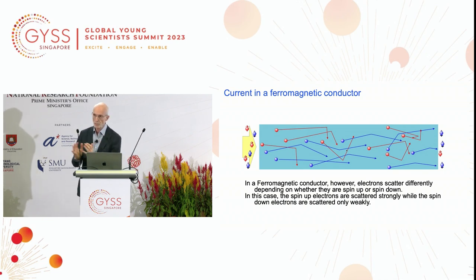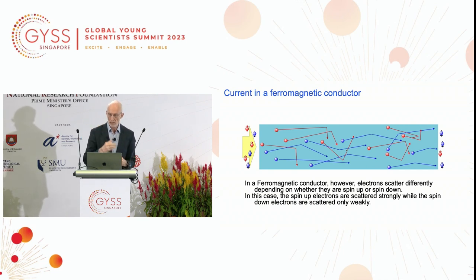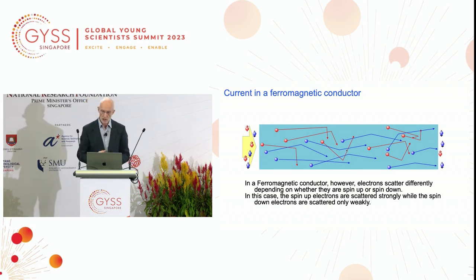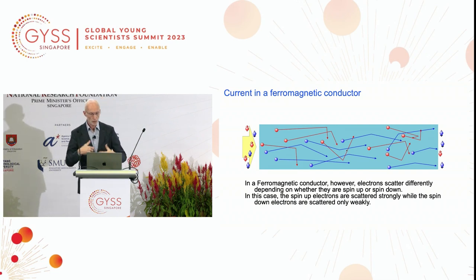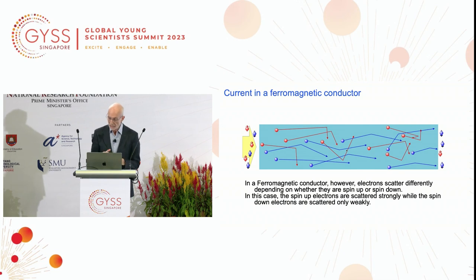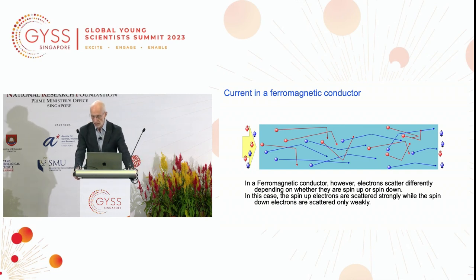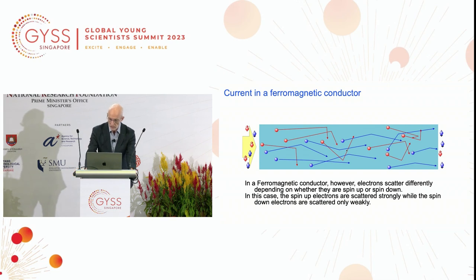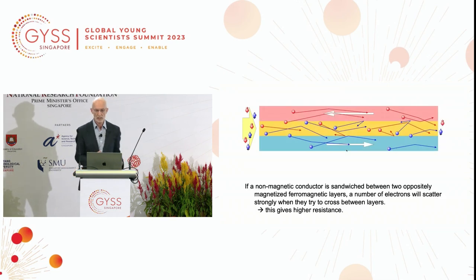It now carries spin polarization, and an important property of spin is not the magnetic moment, it's the spin angular momentum. And this angular momentum we could use if we deliver enough of these electrons which are spin polarized to create a torque, in the same way that in the mechanical world you can create torques from angular momentum. We can create spin torques from spin angular momentum. I'm going to come back to that later, but here the point is that scattering gives rise to a spin polarized current.